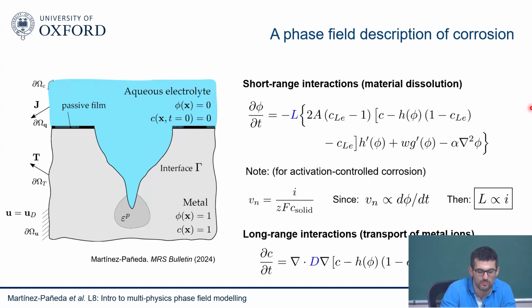You do have a rate-dependent term. This is all fine. There are a few parameters that come into play there, but we can see that basically what governs everything is this mobility coefficient L. And you can show analytically that under conditions of activation control corrosion, this mobility coefficient L is proportional to the corrosion current density. So remember that you have this expression for the velocity of the corrosion front under activation control corrosion conditions. And since this velocity is proportional to the change of the corrosion front, the derivative of the phase field with respect to time, then you can conclude that L is proportional to the corrosion current density.